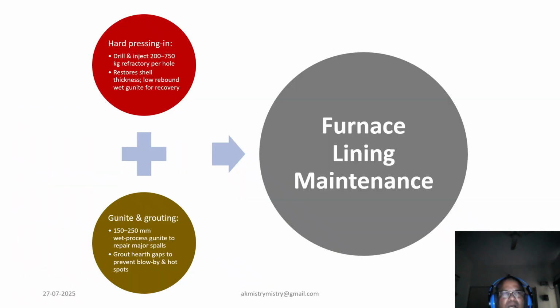So now coming to the prolonged campaign, which requires strategic refractory repair. We can say that hard pressing in 200 to 750 kg of castable per drill hole restores shell thickness. A wet process gunite layer of 150 to 250 mm seals spalls swiftly. Grouting the hearth gap prevents blow by, preserves integrity and avoids hot spots. So these are basically the keys.